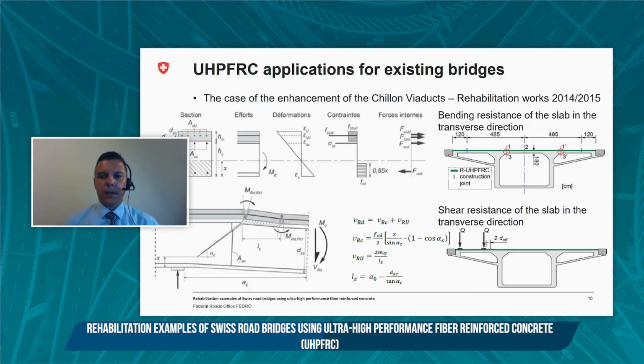The widening of the inclined crack in the concrete section creates a prime action of the ultra-high performance fiber reinforced concrete layer, which resists by bending out of plane in double curvature. Here, this is accompanied by a softening of the concrete in the concrete volume under the layer, called the intermediate crack-induced debonding zone. Now, the contribution of the ultra-high performance fiber reinforced concrete to the shear resistance is thus a function of its bending resistance in double curvature over the length of this zone.